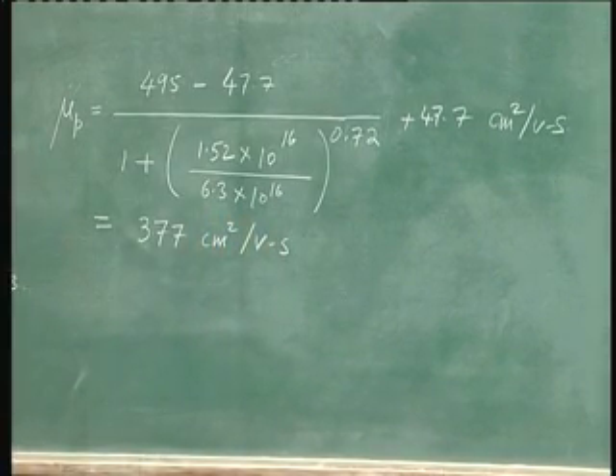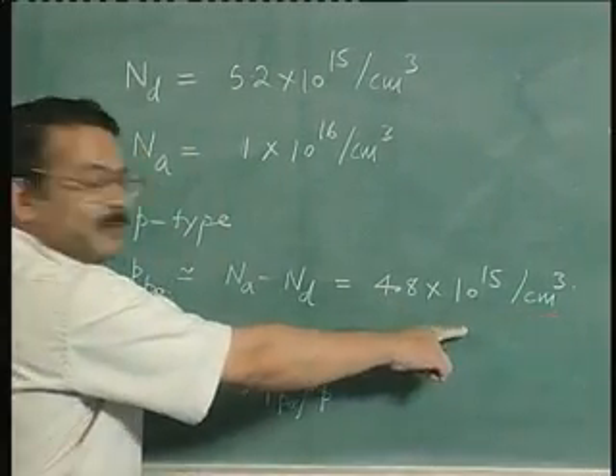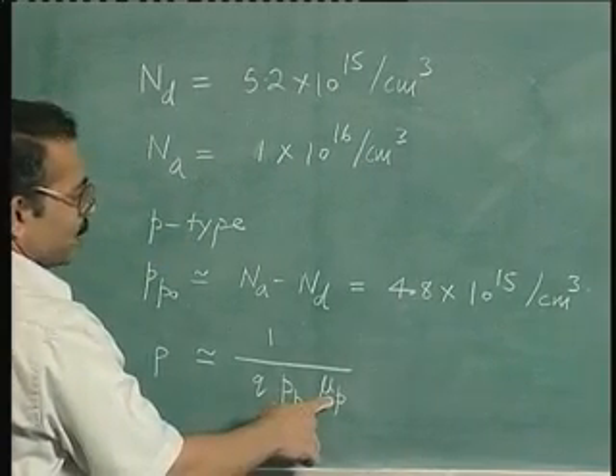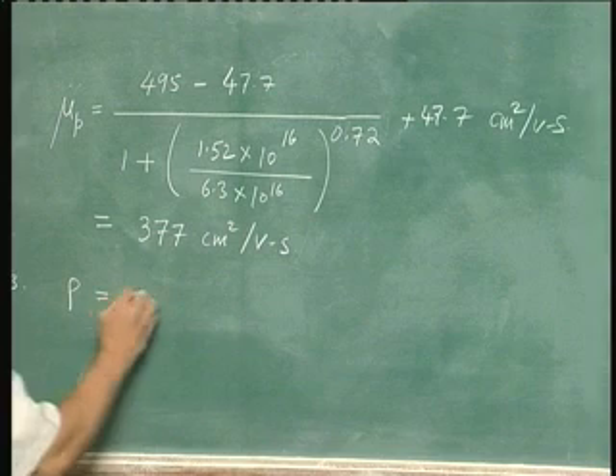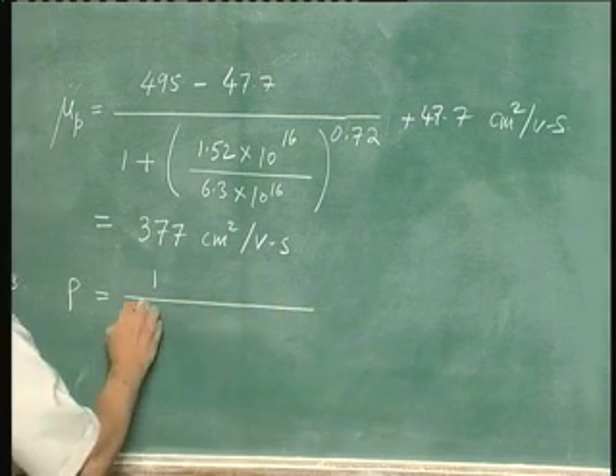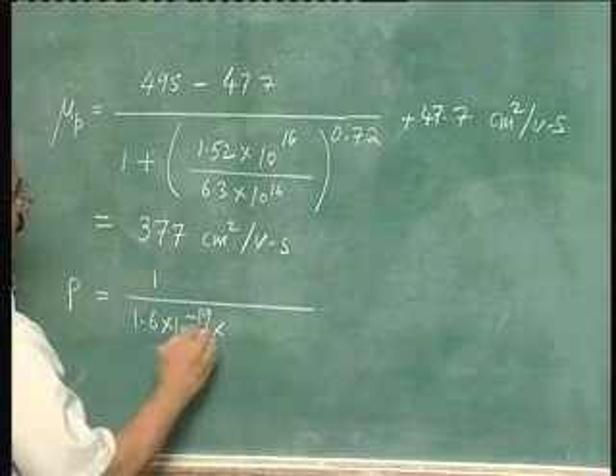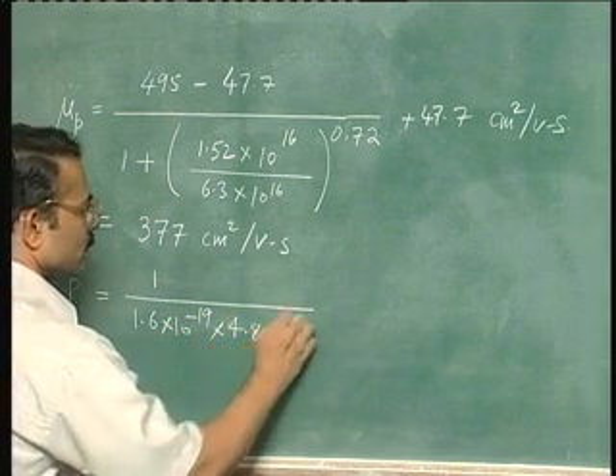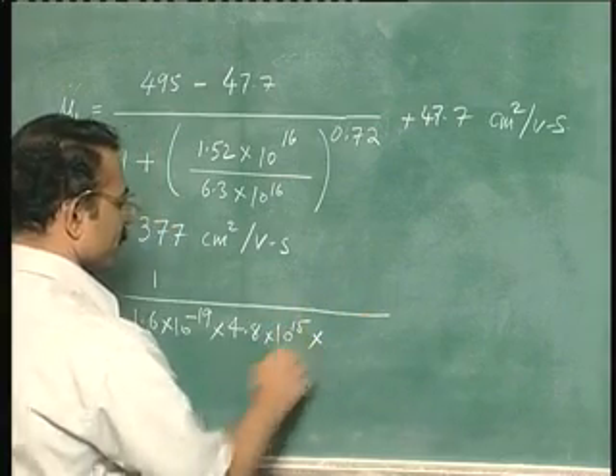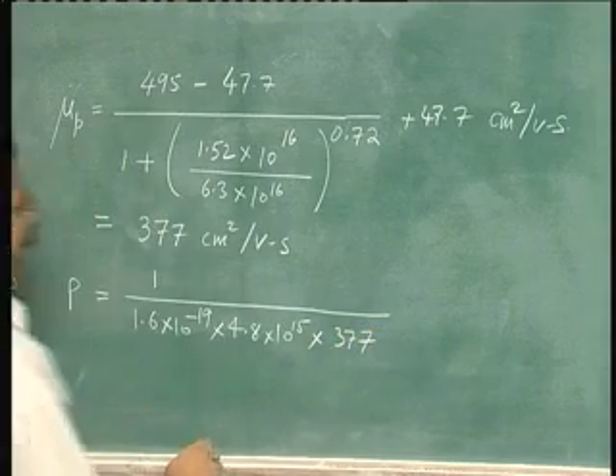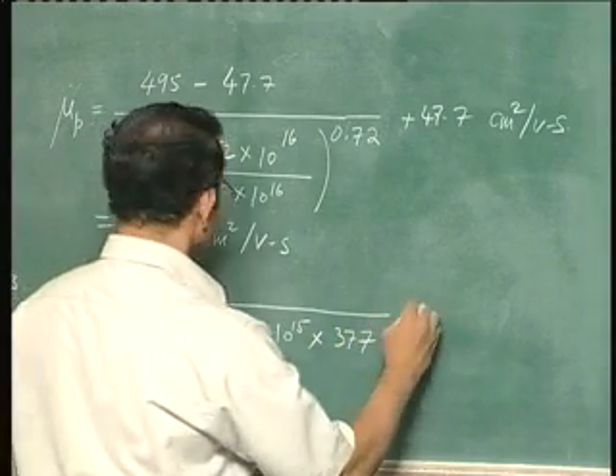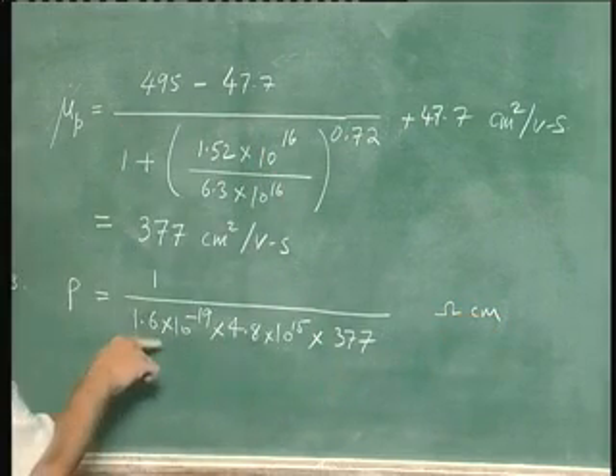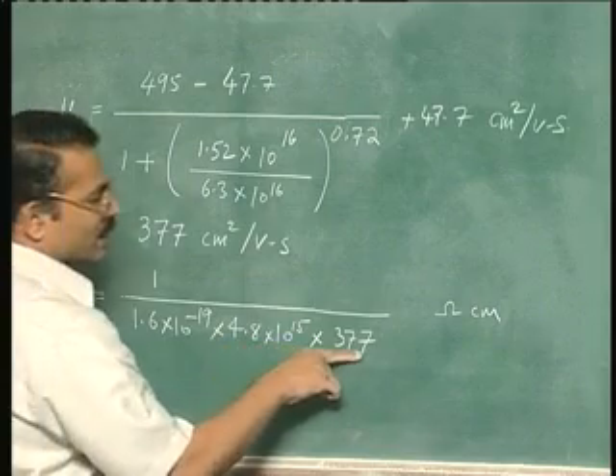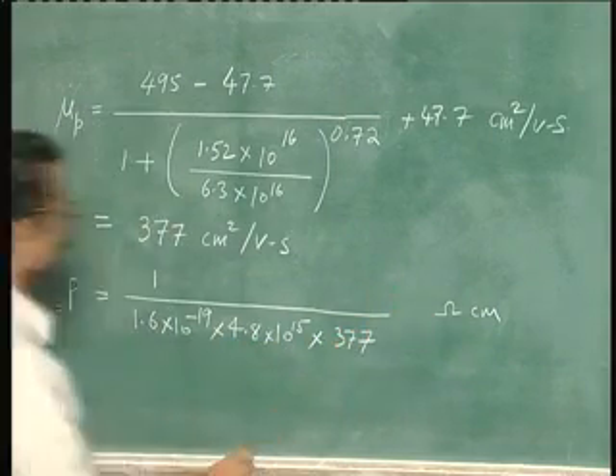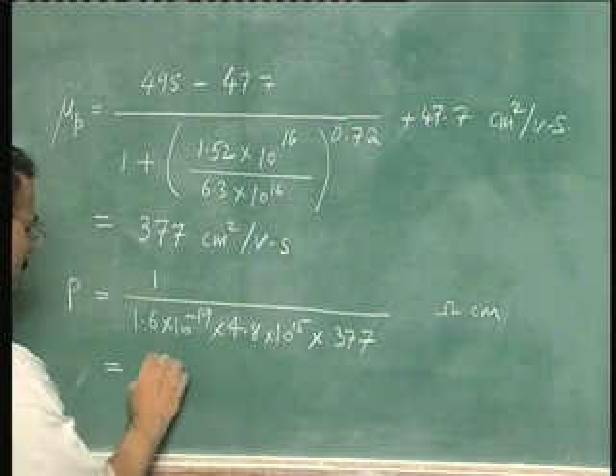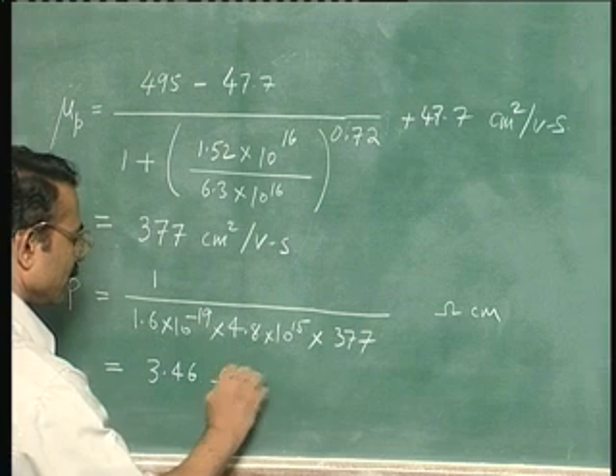So now we can substitute this Pp0, that is this 4.8 into 10 power 15 here, and 377 centimeter square per volt second here, and your resistivity would be 1 by Q into Pp0 into mu p, 377. This is the resistivity, and of course your unit will be ohm centimeter, because this is in coulombs, this is per centimeter cube, and this centimeter square per volt second. We have shown that if you use these units you will get resistivity in ohm centimeter, and the result is 3.46 ohm centimeter.